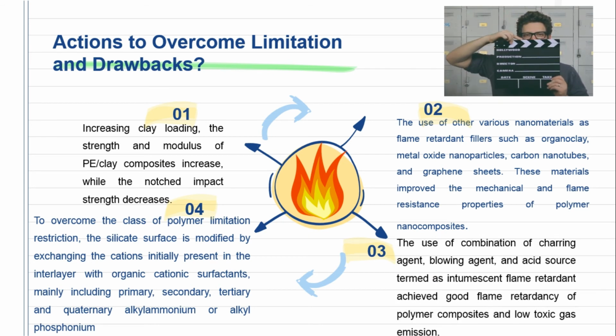Third, the use of combination of charring agent, blowing agent, and acid source, termed as intumescent flame retardant, achieves good flame retardancy of polymer composites and low toxic gas emission. Fourth, to overcome the class of polymer limitation restriction, the silicate surface is modified by exchanging the cation initially present in the interlayer with organic cationic surfactants, mainly including primary, secondary, tertiary, and quaternary alkyl ammonium or alkyl phosphonium.